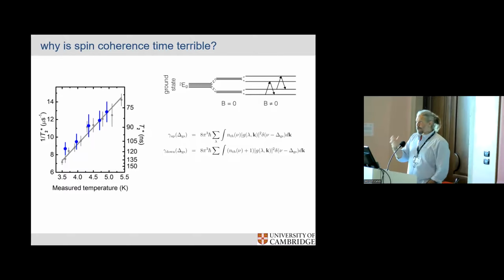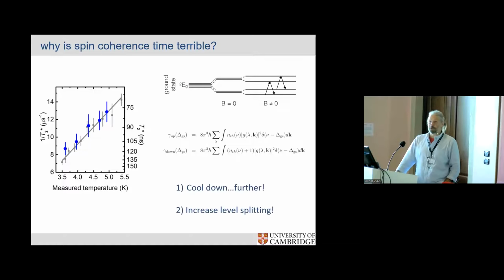So then the quality of your spin is now muddled by the fact that there's an orbital replica of the spin up and down that you have in the system. So that's bad. So there are 2 ways you can fix this. You need to remove the phonons, so they don't do that. Or you increase the energy level splitting so that you probe the larger frequencies required for the phonons, and that also dies off fairly quickly.